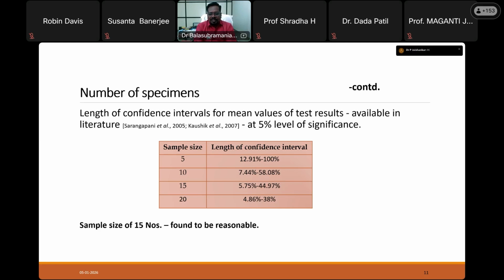Similarly, for a sample size of 15, the length of confidence interval is further drastically reduced to 5.75 to 44.97, and beyond that, if you see, not much of a significant reduction. It was simply reducing to 4.86% to 38%. So that was the bound. Beyond 15, it wasn't coming down. So with the increase in the sample size, the confidence interval was reducing, and beyond that, it was not reducing much. And then 15 samples was found to be reasonable in our study.